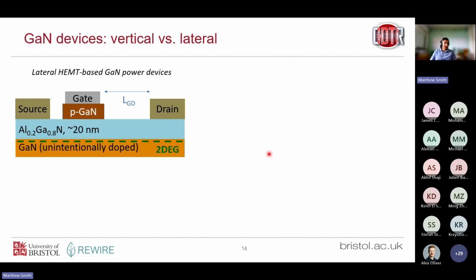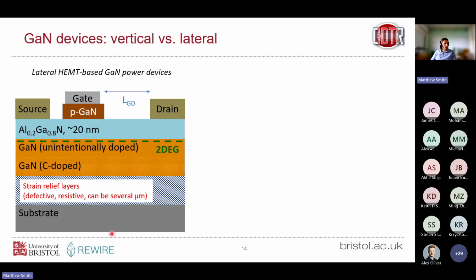So let's dig in a little bit more on how these lateral devices work. So actually, that's what I've shown so far, where we've got this GaN channel and the AlGaN barrier layer, and then maybe something on top to make it enhancement mode. But actually what we have is a lot more going on down here. So we've got our substrate, which is typically silicon or maybe silicon carbide, sapphire, depending on whether we're focused on power or RF devices. But in order to grow our high quality gallium nitride channel, we have to do lots of things between the substrate and the channel. So we have these nucleation and strain relief layers, which can be several microns, and they're defective, resistive, so they're essentially magical layers, we can think of them as, that alleviate strain and account for the mechanical and thermal differences between the gallium nitride and the substrate.